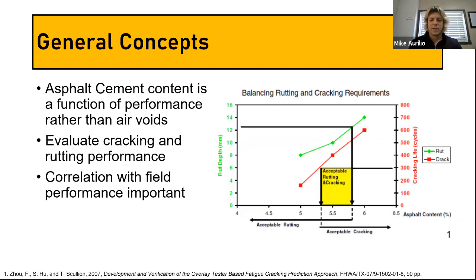So what they find is that there's an acceptable range based on performance for the asphalt cement content. Then they ensure that the air voids are correct for that mix. These tests require obviously some correlation with field performance in order to have a relevance in the lab. But once you have that correlation, you can start to evaluate mixes based on their anticipated performance, and you can start to design things that way.